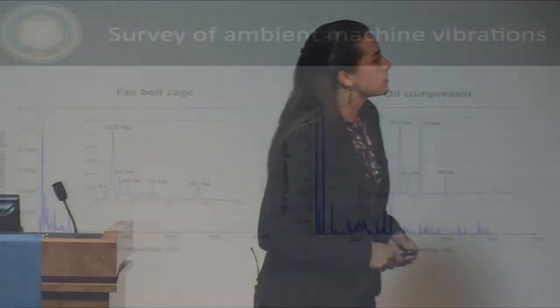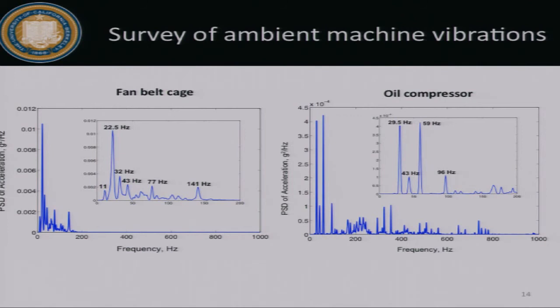And this just shows a power spectral density of a couple of the different sources. This is that fan belt cage and the oil compressor. What I'm trying to show here is that, first of all, above 200 hertz you have pretty much zero energy in the vibrations. Here you have some, but the dominant content is under 200 hertz. In general, all of the vibration sources were similar in the sense that they are low frequency dominated. But if you zoom in to this low frequency range, the dominant frequencies are very different. So what this points to is that you can't have one harvester optimized at one frequency and have that work on any machine. That's important to keep in mind for later as we'll be working on this.